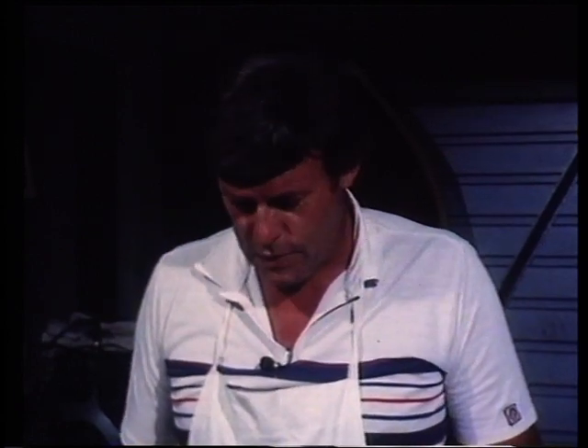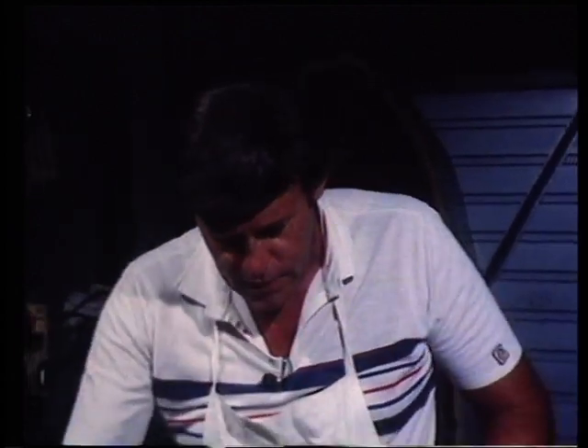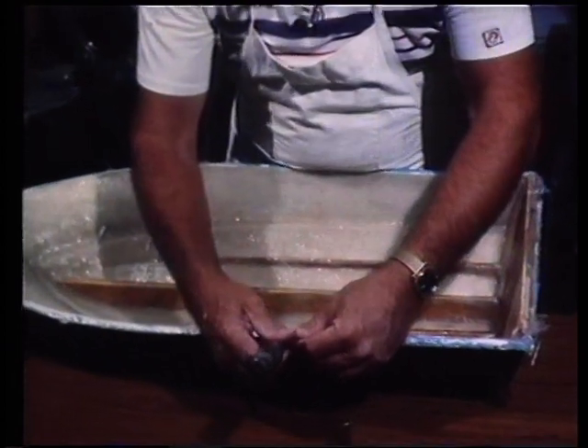Well, we've gone through the entire process. We've waited 24 hours for the laminate inside the whole mould to cure there, and now it's time to release it. And this is where a lot of boats are damaged, or a lot of mouldings are damaged. It's necessary to be very, very careful in the release process.